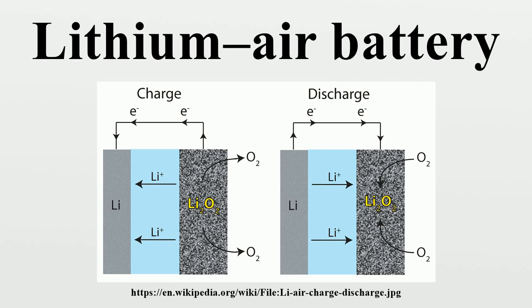Significant drops in cell capacity with increasing discharge rates are another issue. The decrease in cell capacity is attributed to kinetic charge transfer limitations. Since the anodic reaction occurs very quickly, the charge transfer limitations are thought to occur at the cathode. Stability. Long-term battery operation requires chemical stability of all cell components. Current cell designs show poor resistance to oxidation by reaction products and intermediates. Many aqueous electrolytes are volatile and can evaporate over time.